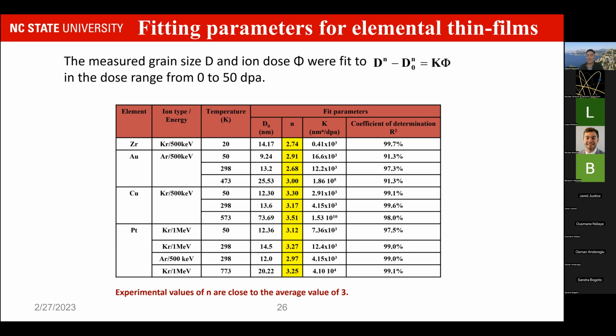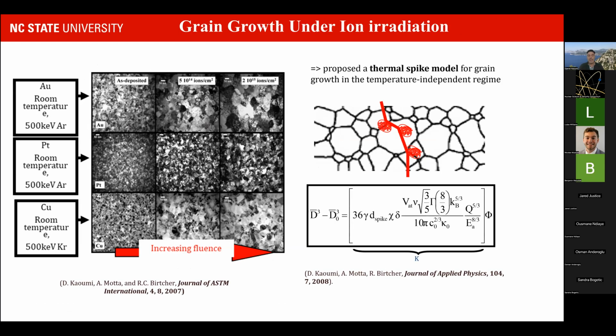And the whole goal of the study was to try to develop a model that will account for this kinetics. For the sake of time, I'm not going to go over the derivation of it. It's actually in this paper here from 2008. Based on the literature and previous work, we developed a model that accounted for the kinetics. The idea was that this thermal spike model for grain growth was based on the idea that ions, as they go through the material, will create those point defect cascades here and there whenever you have a transfer of energy that is large enough.